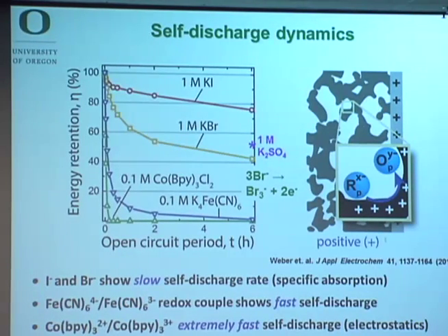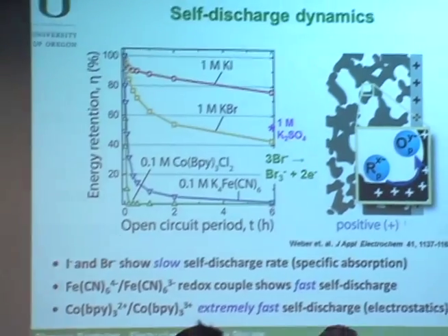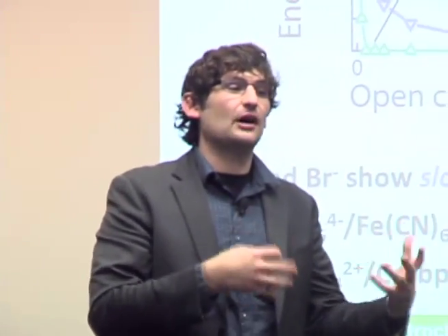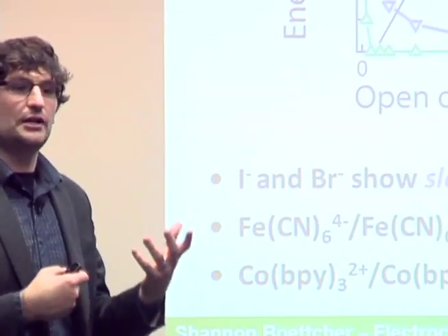We wanted to understand this a little better, so we did a couple of control experiments. We used some well-known outer sphere, spherical 1-electron redox couples, and we wanted to look at whether, for example, the charge of the redox species made a difference. If this is the positive electrode, there's a bunch of positive charge sitting on the carbon. It's been electrostatically charged positive, and to counteract that positive charge, you need negative charge in the double layer. That double layer charge could come from the iodide or bromide counterions. Now, if you put in a redox species that's also positively charged, electrostatically it would not want to stay in this nanoporous host that's positively charged also.